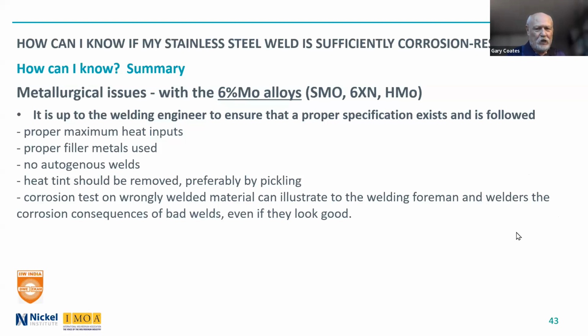I've done that before. I've showed them a sample of an autogenous weld with huge pits in it from the test, and they are shocked in some ways and say, okay, I better not do it, even if it may take 6 months for it actually to show up in practice.